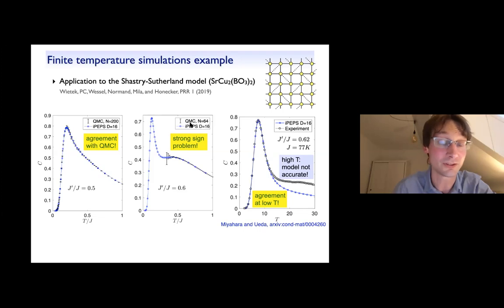This is not even standard quantum Monte Carlo, but an improved one where they managed to weaken the sign problem. So to get these couplings, and even up to here, but then to get into the relevant regime, so around 0.62, you can't do this with quantum Monte Carlo, but with iPEPS it was a useful first benchmark to get some interesting results. But of course, if you take a more challenging model, then we expect to get into trouble as we go to lower and lower temperatures.